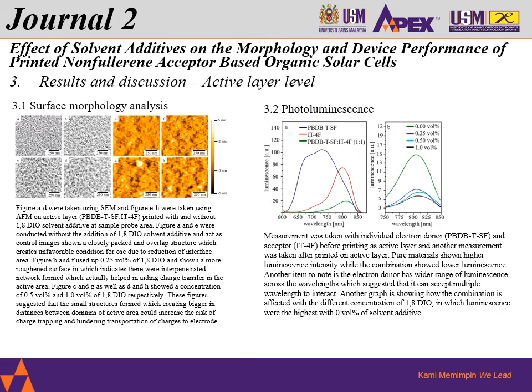So under results and discussion at the active layer level, the surface morphological analysis from SEM and AFM images. Over here, the gray photo shows the SEM images, and then the orange or gold photo here comes from TEM. Sorry, AFM. And then different concentrations of DIO were tested, which is 0%, 0.25%, 0.5%, as well as 1%.